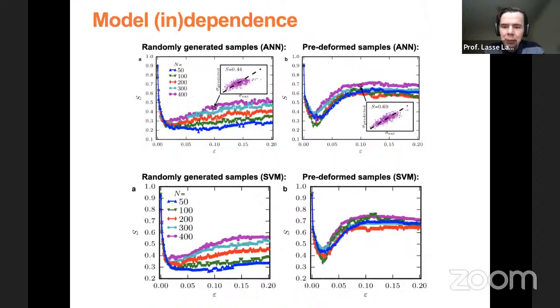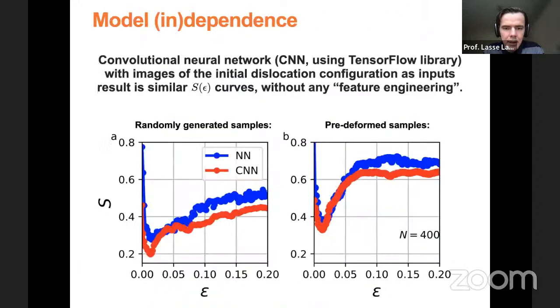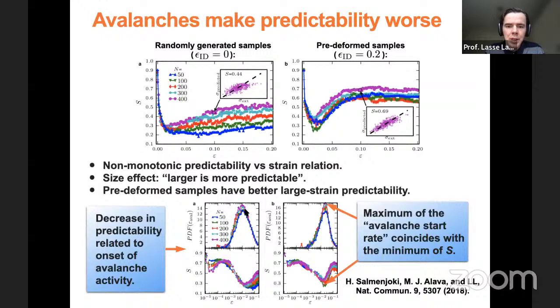And now the point is that what we measure here is the density of avalanche onset as a function of strain. So at the maximum, you tend to start lots of avalanches, and because these are hard to predict, we have lots of them. Then it's also hard to predict the overall stress value at that strain. That's the argument. I don't know if it actually is true, but at least we have a very convincing correlation between the position of this maximum here and the minimum here. Yeah, that is very clear.